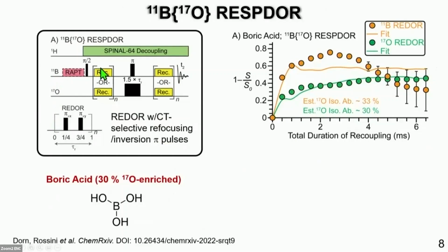So we first perform boron-oxygen REDOR experiments to determine whether we can apply the recoupling to the boron or oxygen spins to reintroduce the dipolar interaction under magic angle spinning. So as you can see here, here are some REDOR spectra with recoupling applied either to the boron spins in orange, or the oxygen spins in green. When you apply recoupling to boron, you get a significant amount more signal dephasing. However, the dephasing curve tends towards zero at longer durations of recoupling. And this is because it's much more sensitive to fluctuations in the magic angle spinning frequency when you apply the recoupling to the observed spins.